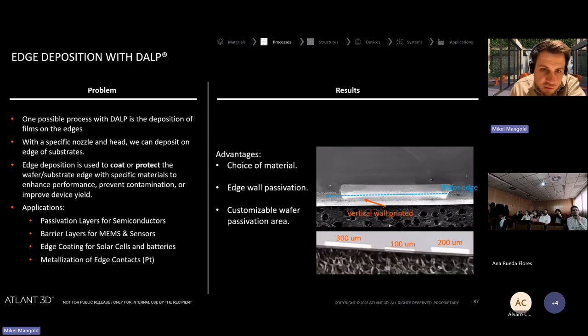And this one, I think, is what I was mentioning to you, the edge passivation for advanced packaging. To coat the wall of a material on the side like that is extremely difficult. I know it's feasible, but I think it's multiple steps currently. So we were able to locally control how much edge sidewall we coat. As you can see here, 300 micrometer, 200. We were completely able to control that on the wafer edge.